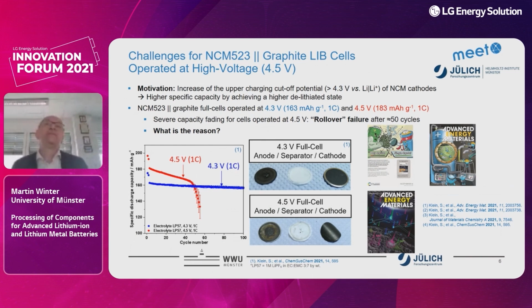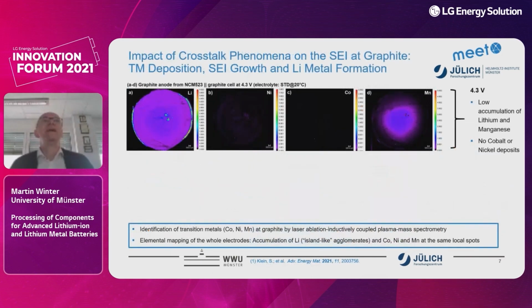If we look at just a simple visual inspection of coin cells made from graphite NMC cells, we see at 4.3 volt and 4.5 volt that we have depositions on the anode in both cases, but the depositions at 4.5 volt are much more than at 4.3 volt. And we have investigated this in several papers, some of them quite prominently placed in journals, which are mentioned on this slide.